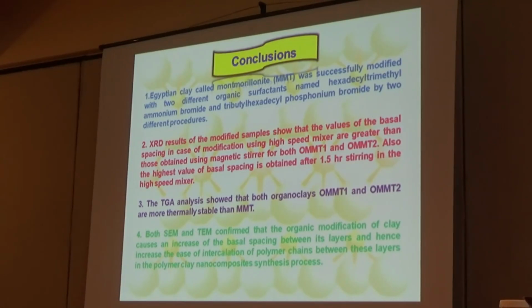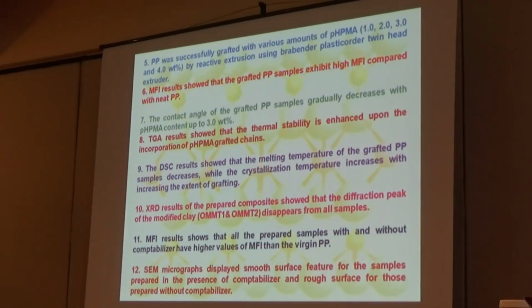Thermogravimetric analysis showed that both organoclays are more thermally stable than montmorillonite clay itself. Both scanning electron microscope and transmission electron microscope confirmed that organic modification of clay causes an increase in the basal spacing value between the layers. Polypropylene was successfully grafted with various amounts of p-hydroxy-N-phenyl maleimide monomer. Melt flow index results show that the grafted polypropylene samples exhibit high melt flow index compared with the neat polypropylene.